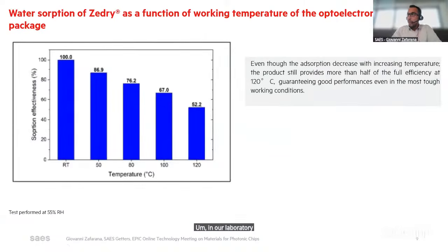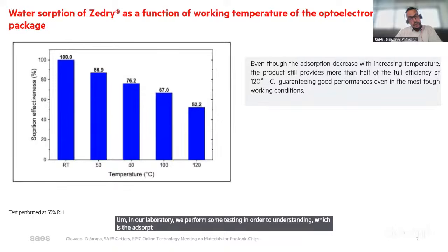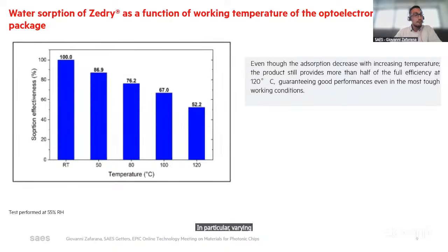In our laboratory, we perform some tests in order to understand the adsorption performance, in particular changing the temperature of the devices. We saw that increasing the temperature from room temperature to 120 Celsius, the adsorption still remained at 50% of the effective absorption. So the question is, what is the remaining water inside the package? For that, we are performing the isotherm of water in order to understand, increasing the temperature, what humidity is still remaining inside the packages.